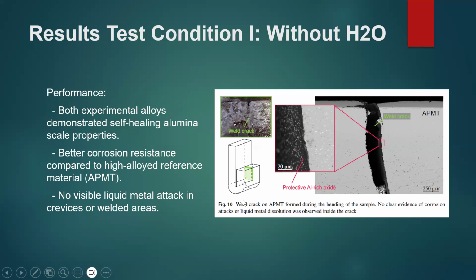We can see this weld crack of APMT formed during the bending of the sample. No clear corrosion attack or liquid dissolution was observed in the crack. So you can see it's a weld crack.